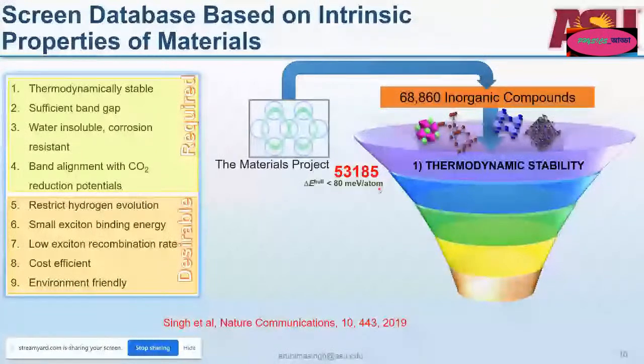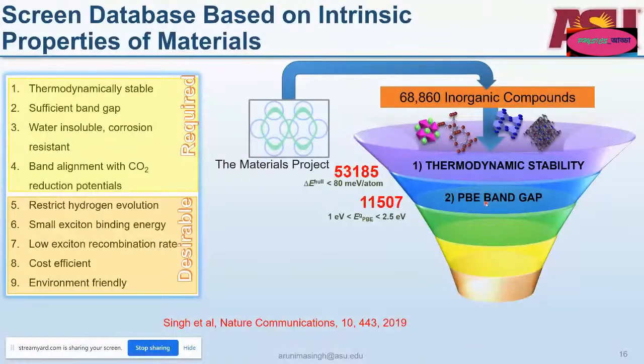The second criterion which we chose was looking at the band gaps of the material, and the Materials Project has the band gaps computed using the PBE and PBE+U functionals. And as I mentioned earlier, even though the density functional theory simulations are in principle exact, the functionals have an approximation to them, which makes their band gaps inaccurate by about 30% or so in most cases.